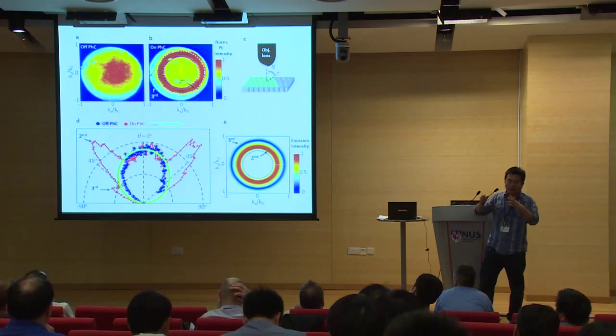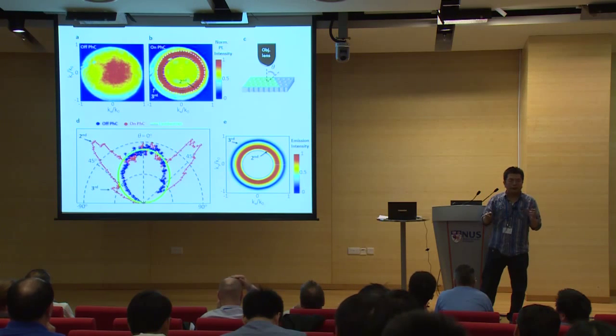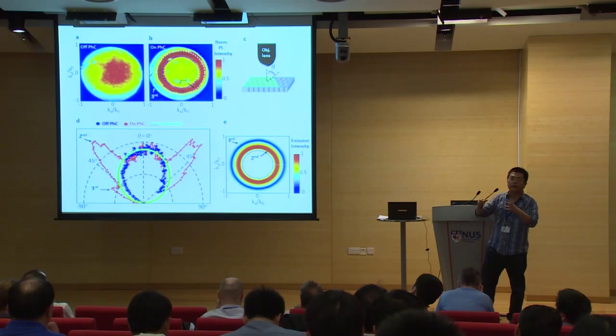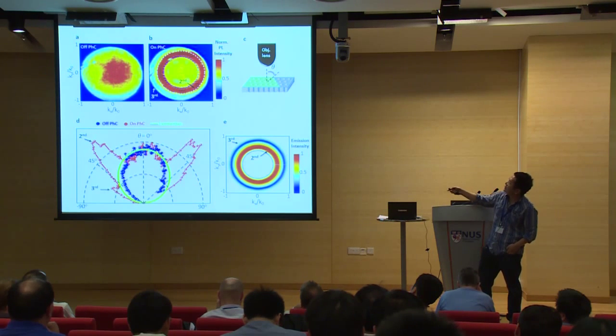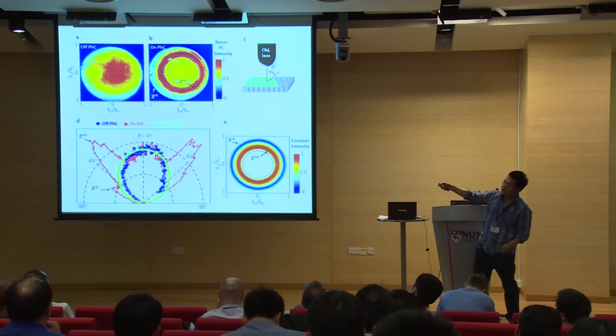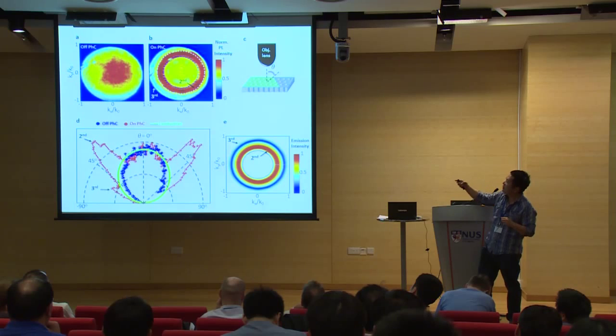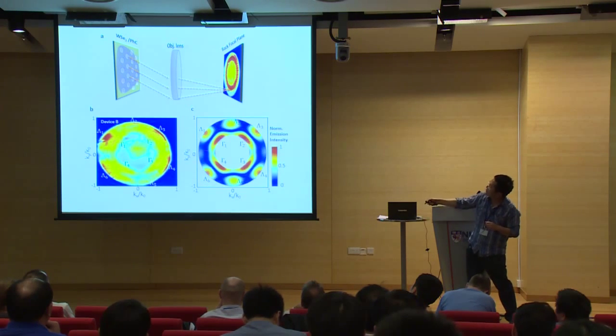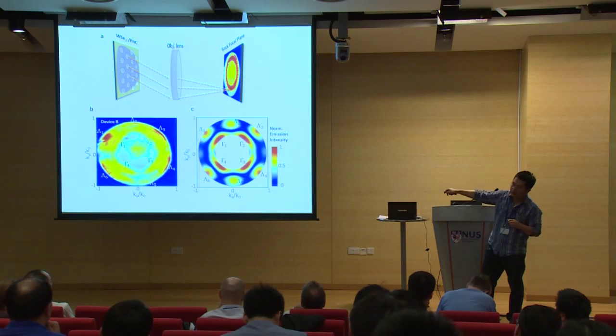Basically, the emitting light is on the order of 800 nanometers, but the photonic crystal cavity lattice is on the order of 100 nanometers. So there's a strong interference effect, depending on the crystal lattice of these photonic crystals. And the pattern of emission can be modulated. For this particular case, this is sort of an optical antenna feature, right? We have the ring here. If we fabricate a different type of photonic crystal cavity, we change the patterns, and we can have this more complicated pattern. The right hand here is theoretical simulations, and the left bottom is the measurements.